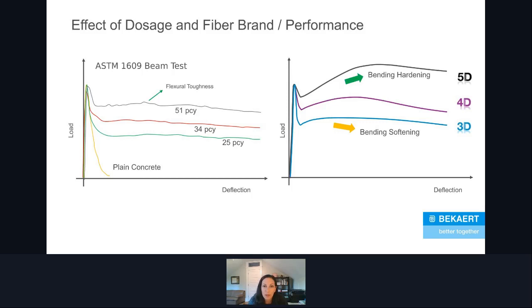Secondly is the ability of the 5D fibers to achieve bending hardening behavior. Actually, prior to the invention of 5D fibers, it was not thought possible that bending hardening behavior could be achieved with a steel fiber reinforcing solution. So it actually is pretty special in the market that we have that available. And that's one of the reasons why you can use 5D fibers in those really more rigorous structural applications, because bending hardening is also what rebar does as well.